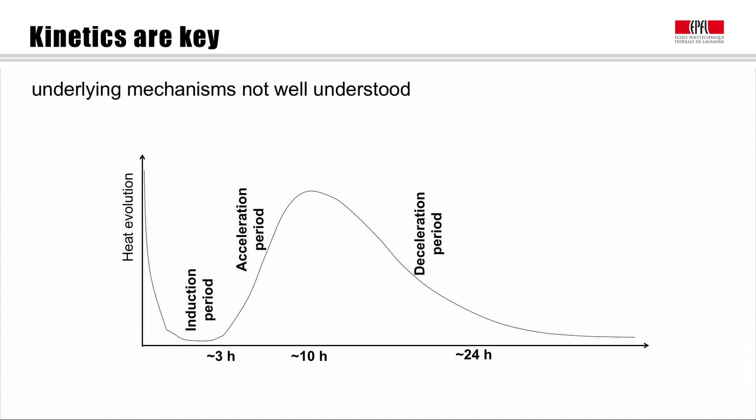Here we're going to look first at the hydration of the calcium silicate phases. This shows the typical hydration curve for tricalcium silicate. What you see is that initially we get a very high rate of heat evolution and then very quickly the rate of heat evolution, that's to say the rate of reaction, falls away and we get this period of very slow reaction during a few hours and this is usually called the induction period.